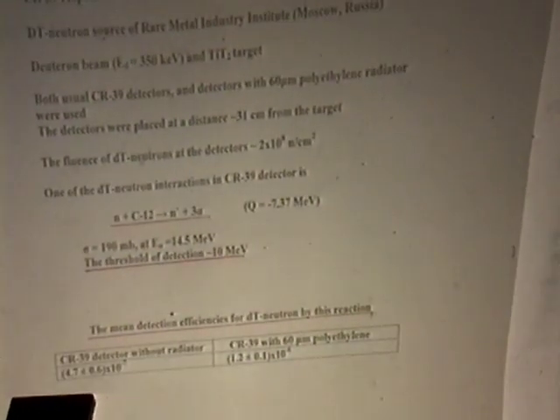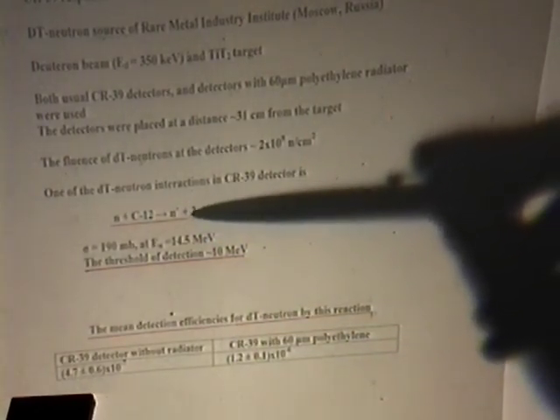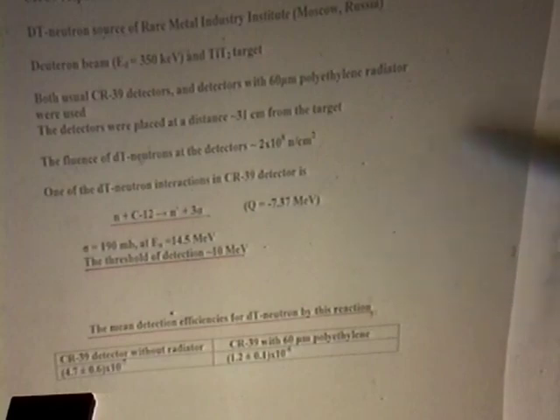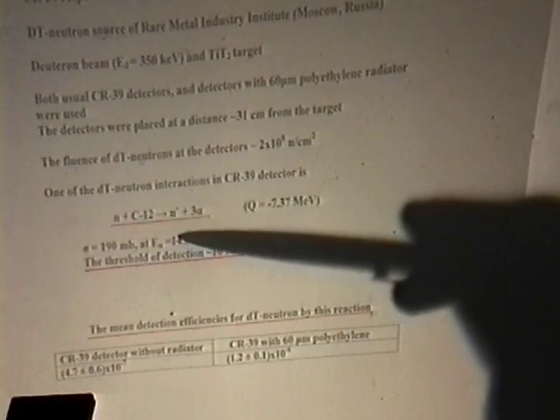One of the DT neutron interactions in the CR39 detector is the inelastic scattering of neutron on C12 nuclei, causing the decay of this nucleus into 3 alpha particles. This reaction has a cross section near 190 millibarn at the neutron energy 14.5 MeV, and the detection threshold for DT neutrons by this reaction in CR39 detector is near 10 MeV.